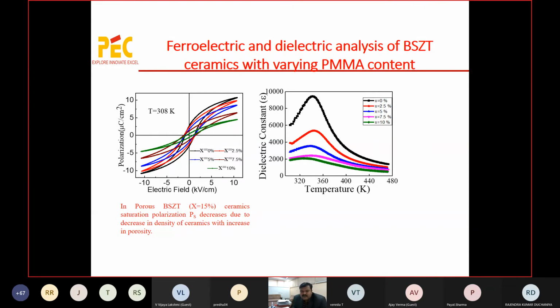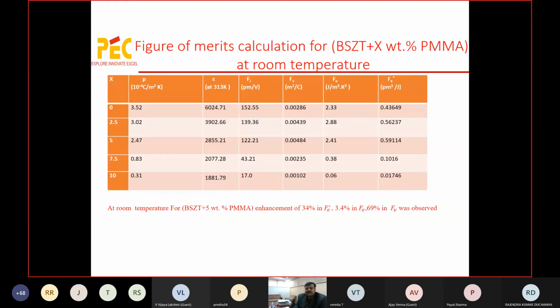For x is equal to 0, you will have the black curve, and for x is equal to 10%, you have the green curve, right? For x is equal to 0, nearly at 350, you have the dielectric constant nearly 9500, and for x is equal to 10%, it is less than 2000. So these are different figures of merit she observed for these materials to show that these are very good pyroelectrics.